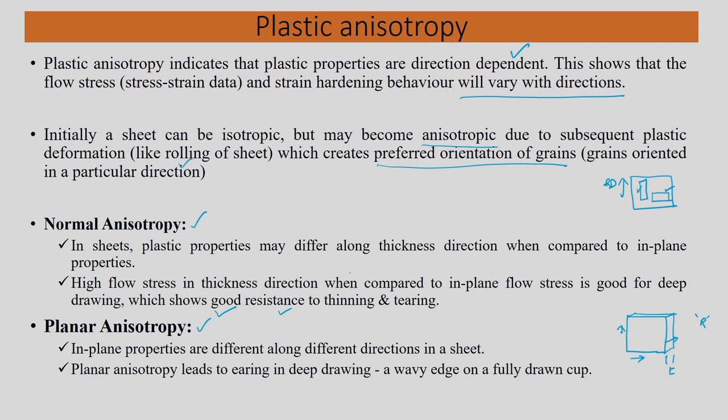On the other hand, there is another parameter called planar anisotropy. Okay. Planar anisotropy means in the plane itself, the properties may vary. So, in-plane properties are different along different directions in a sheet. In-plane means in one plane other than the thickness direction, the properties are going to be different. And we are also going to quantify one good property which in a way describes that, and you will see that it is going to actually control earing, which is a defect